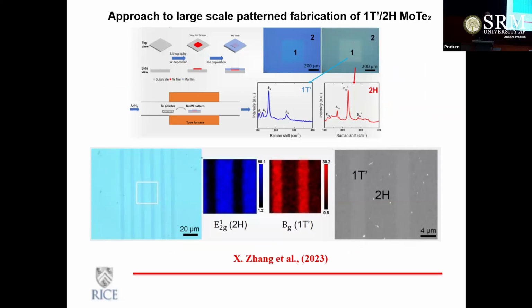Now, I mentioned two different scenarios when you talk about lateral junctions. I talked about a metal insulator system, boron nitride and graphene. I talked about two semiconductors joined together, right? Different band gaps, tungsten sulfide, molybdenum sulfide with different compositions. I can also think about the same composition, but different phases. Initially I started to say that the same material can have different phases. So this is an interesting material, molybdenum ditelluride, which exists in two different crystallographic phases. And I could also engineer these phases in a single atom layer in the plane. So again, molybdenum telluride exists in 1T prime phase, which is metal, and 2H phase, which is semiconductor.